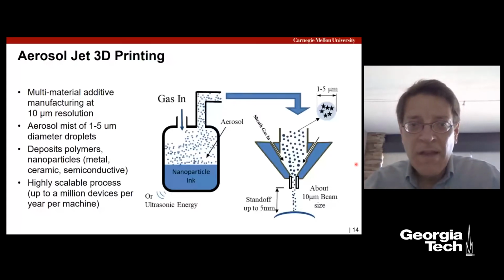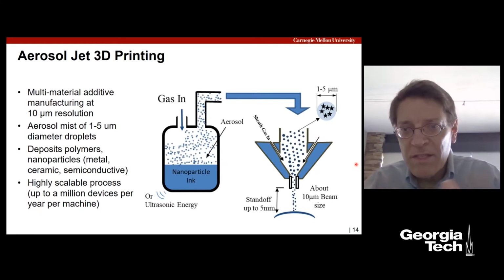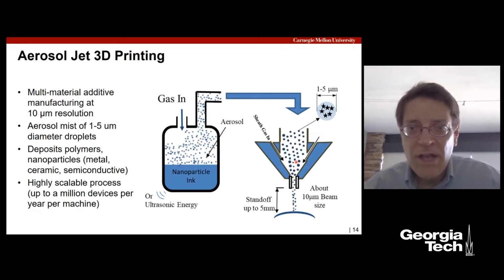That ink can have nanoparticles in it. It can simply be polymers dissolved in a solvent. These droplets, micron scale droplets in an aerosol, then get blown through a tube and through a nozzle. And the key is that there's a sheath gas on the nozzle that focuses this into a stream that you can then get direct write.